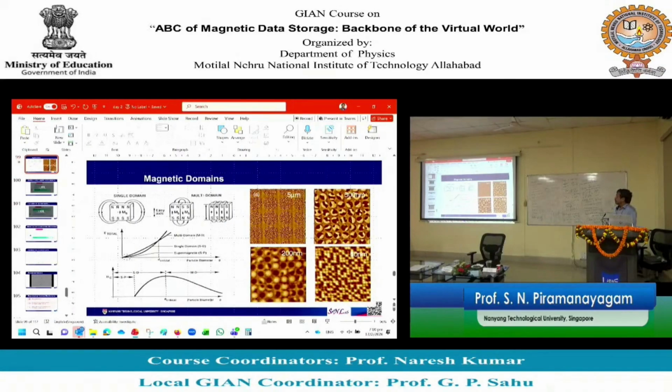So, in the case of magnetism, if the objects are very large usually, then there will be multiple domains like this, but if the objects are small, then they will be in a single domain; they may not form any domain. So, within this 50 nanometer, the system won't form 2 or 4 domains, because there will be more energy to be spent. Within 50 nanometer, there are only fewer spins, right? You have a limited volume, so limited atoms. So, there are not too many parallel spins. The magnetostatic energy is not going to be high.